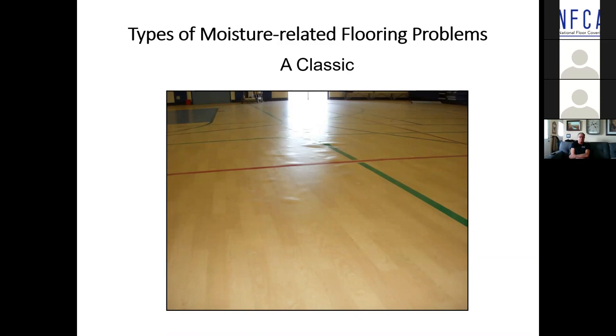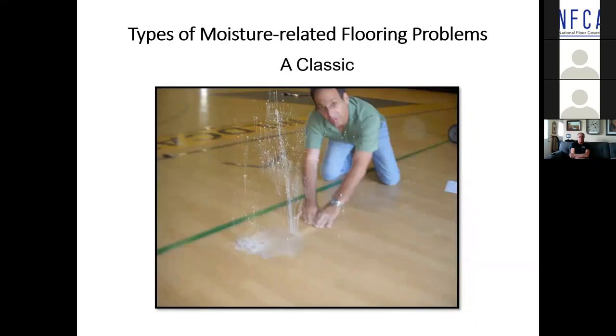What's interesting, my colleague, when we see these blisters, we typically find them to be fluid filled, okay? And what we would typically do is puncture that blister, take a syringe, draw the liquid out, put it into glass bottles with steel caps, wrap it in aluminum foil, and send it to the lab for chemical analysis. And we did that. But my colleague couldn't resist. He said, quick, grab the camera. And we call this Old Faithful.